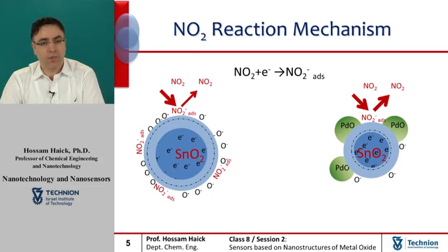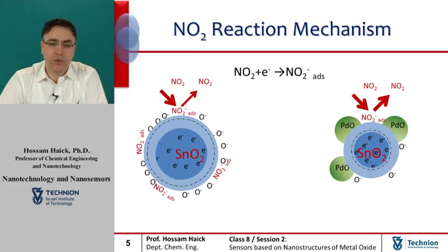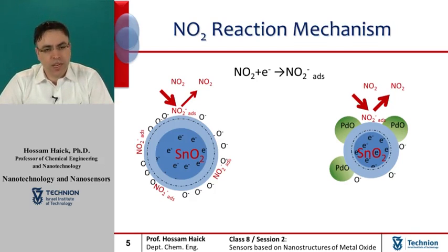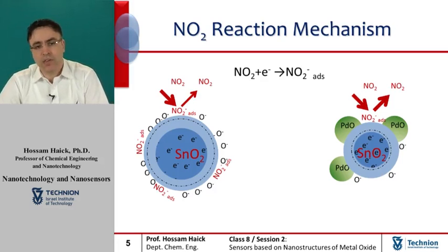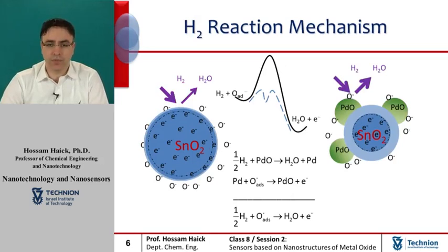On the other hand, when palladium oxide is reduced to palladium on contact with the reducing gases, the resistance decreases by back electron transfer from the palladium to the tin oxide. The difference in the electric resistance of the tin oxide induced by a change between the oxidized and reduced states of the palladium is often large, thus giving rise to a large increase in the response to the reducing gases.